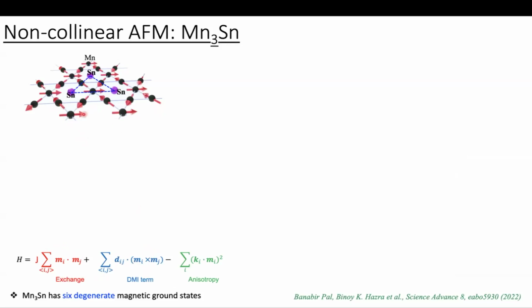So when it is perfectly 120 degrees, the net moment is exactly zero. But due to the presence of small in-plane anisotropy, this breaks the 120-degree antiferromagnetic ordering, and the manganese spins tilt a little bit, which generates a finite net moment. And this tiny moment basically controls the domain structure of this manganese-3 tin compound. It shows exotic magnetotransport properties like anomalous Hall effect, anomalous Nernst effect, and magneto-optical Kerr effect, due to controlling this domain structure by the small in-plane moment.